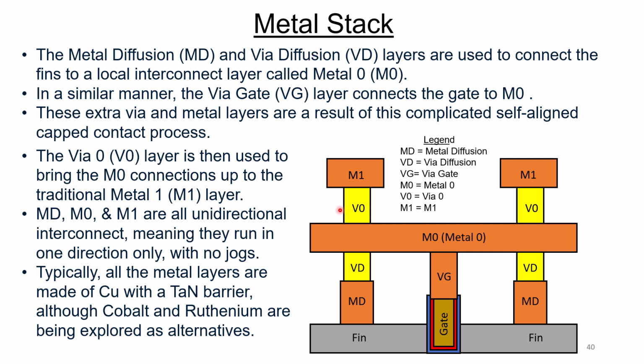So the MD, M0, and M1 are all unidirectional interconnect layers, meaning they run in one direction only, no jogs. And typically all the metal layers are made of copper with a tantalum nitride barrier. Now, as the geometries have grown smaller, the barrier metal is taking up more and more of the area, or the volume, of the conductor. So they're looking at other metals that might not need a barrier metal or that might be more conductive at low pitches. And cobalt and ruthenium are being explored as alternatives to the copper metal with a tantalum nitride barrier.